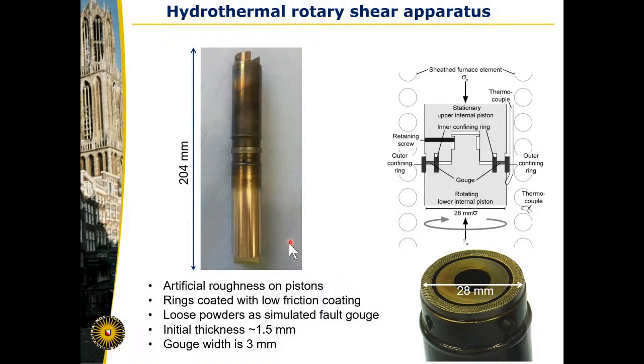So what does the sample assembly look like? It's this René nickel alloy material, which is ring shaped with an outer diameter of 28 millimeter and an inside diameter of 22 millimeter. The gouge layer is deposited on this roughened surface. We use a loose powder as a simulated fault gouge. We have rings that confine that powder, and we close the assembly and we rotate one side while we keep the other side stationary. And then that's surrounded by a furnace which can go up to 700 degrees C.